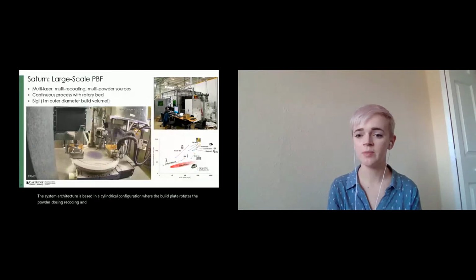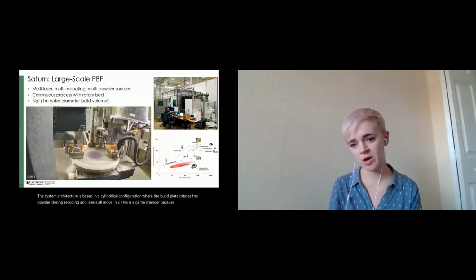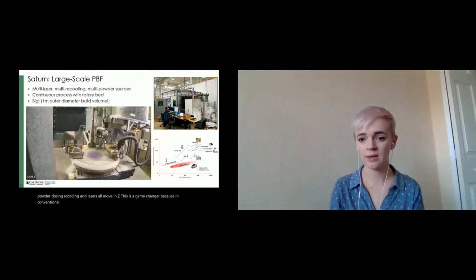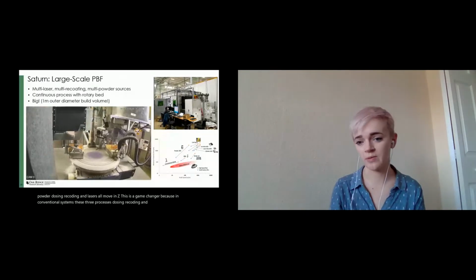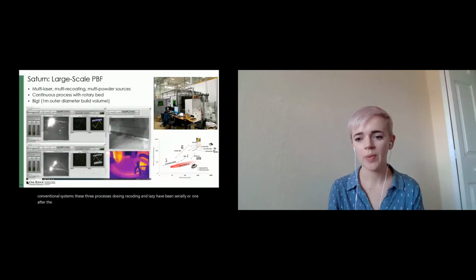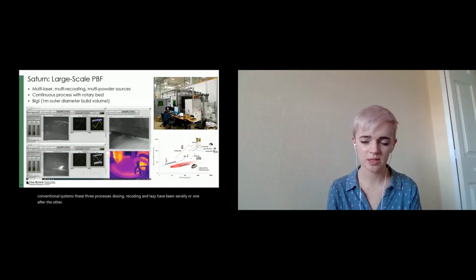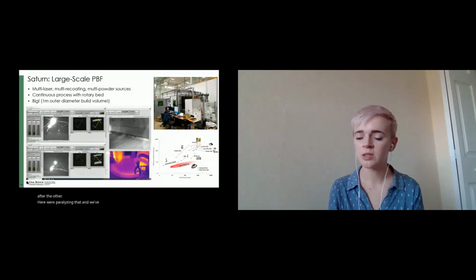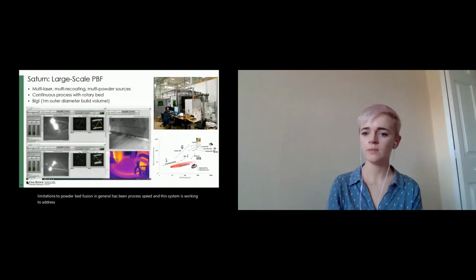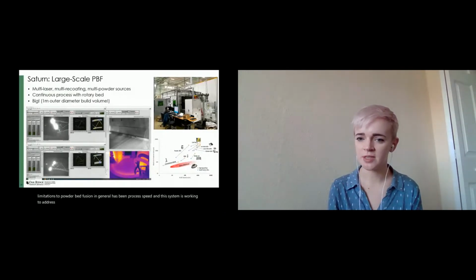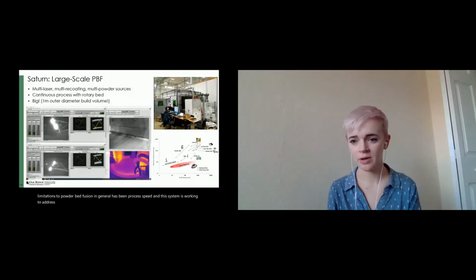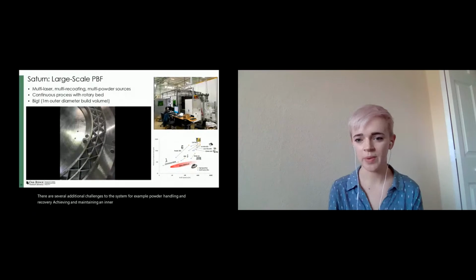This is a game changer because in conventional systems, these three processes, dosing, recoating, and lasing, happen serially or one after the other. Here, we're parallelizing that, and we've made two sites for this to happen. One of the major limitations to powder bed fusion in general has been process speed, and this system is working to address exactly that. There are several additional challenges to this system, for example, powder handling and recovery, achieving and maintaining an inert environment during printing, and process and toolpath planning, but we're making exciting headway.